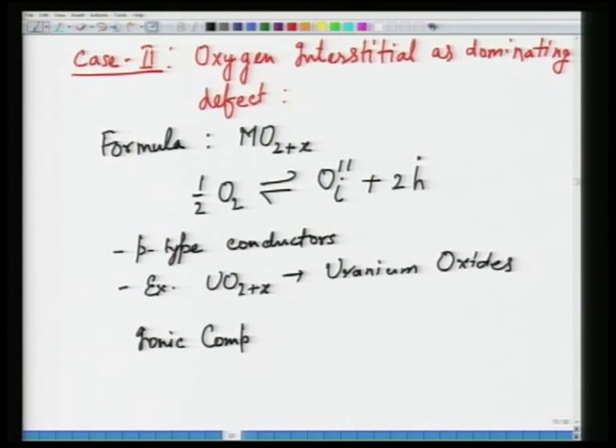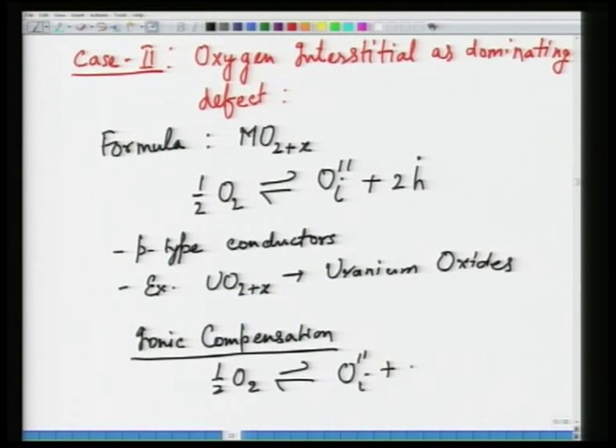Ionic compensation would mean two of the metal sites will be oxidized, but again as I said, in both of these cases the materials prefer to be in the form of p-type conductors by creation of extra holes. So, this is the basis for formation of defects in non-stoichiometric oxides. We have discussed two of these cases and looked at the examples, whether it is oxygen excess or oxygen deficient.